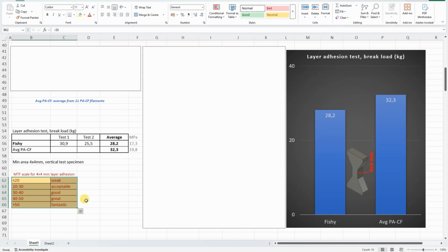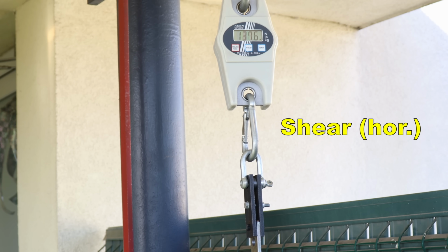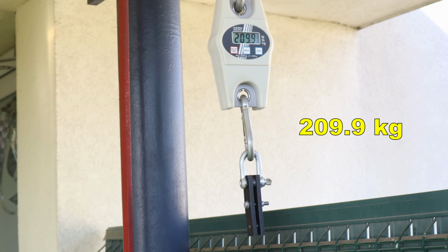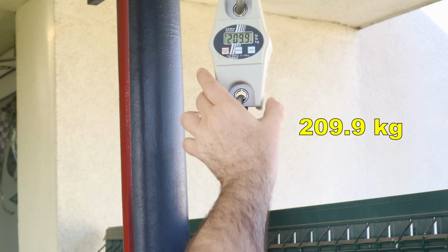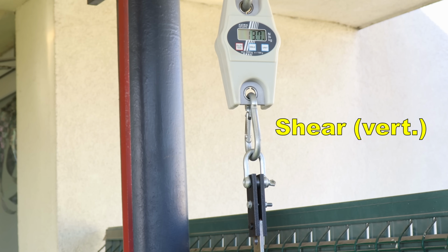Layer adhesion, vertically printed. Here you can see my rating for this type of the test object, and we can see that this filament is a little bit weaker compared to the average PA-CF, and it is somewhere on the edge between acceptable and good. Shear test, horizontally printed. Oh, a little bit above maximum for this hanging scale.